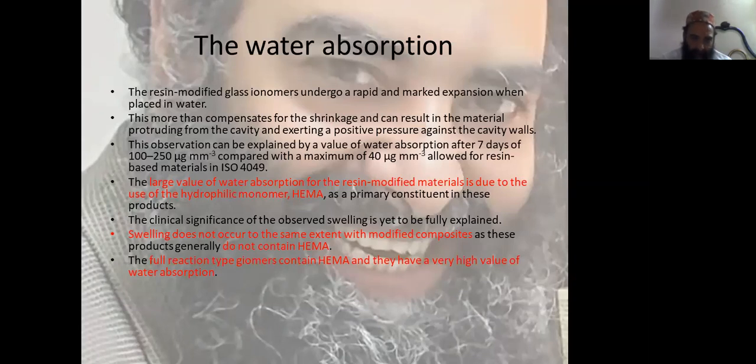The large value of water absorption for the resin modified material is due to the use of the hydrophilic monomer, HEMA, hydroxyethyl methacrylate, as the primary constituent in these products.